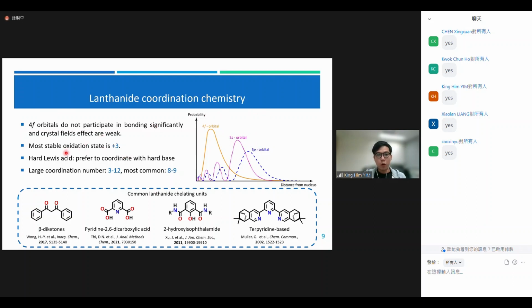So the most stable oxidation state of lanthanide is +3, although you can still find some of them are +2, for example europium, and also maybe cerium is +4. Because of this +3 charge, lanthanide becomes a hard Lewis acid and prefers to coordinate with hard bases, for example O and N. And lanthanide exhibits a very large coordination number from 3 to 12.